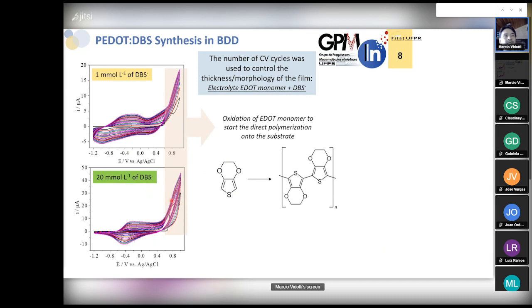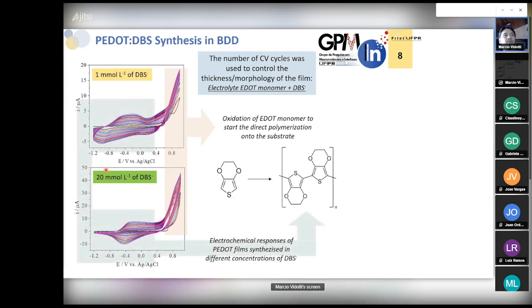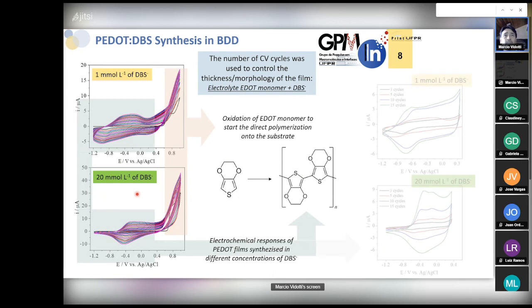So as this potential window is achieved, you can see the second region over here. So we can observe the electrochemical response of this modified electrode at the same time we are running the electropolymerization. So the cycles are increasing. It's direct evidence that we are growing more material on the electrode surface.